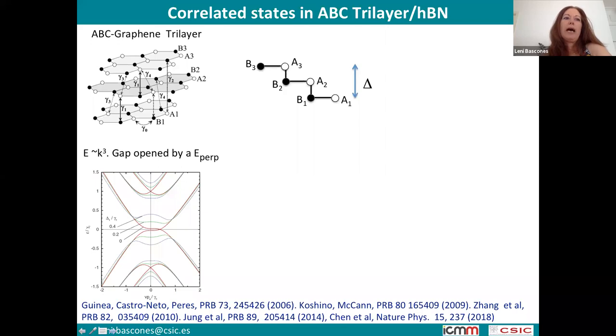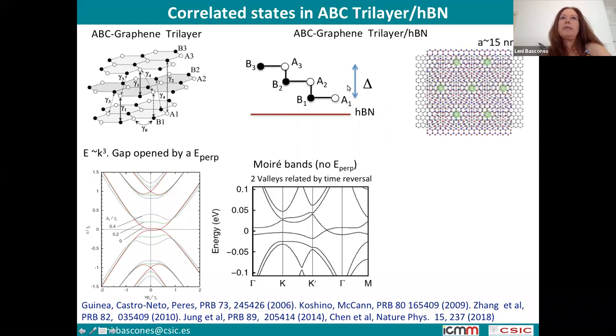So if we now align this system with the boron nitride, which also has a hexagonal lattice, but a slightly different lattice structure, we have the moiré, which has a triangular lattice with a lattice constant of the order of 15 nanometers. In this big superstructure there is a folding of the bands, and we see that we get some flat bands, okay?